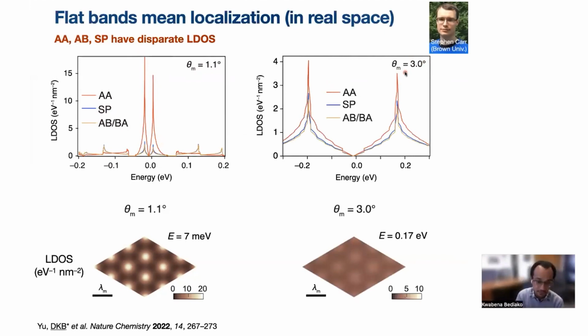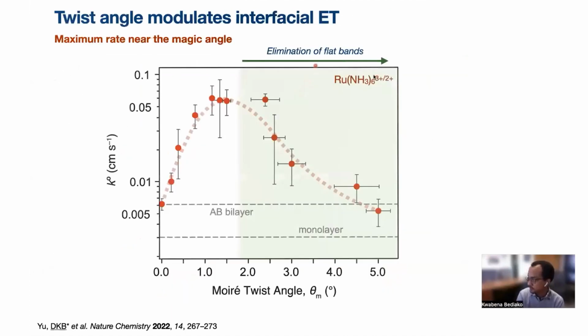And so a number of things come out of this. One is that at large angles, you have this smearing out of the electron wave function, and you also have much less localization, so no flat bands at larger angles. And so we can understand this drop off in the rate constant for our ruthenium three-two couple as simply arising because at large angles we're eliminating the flat bands from our electrodes.